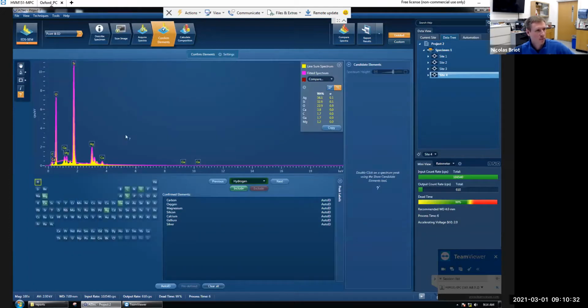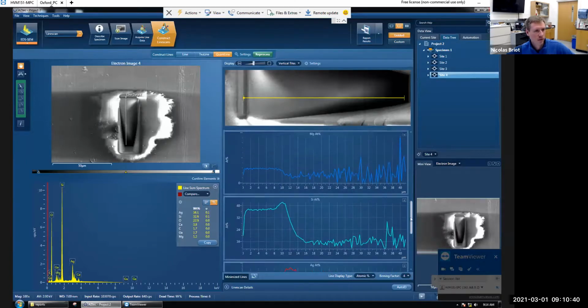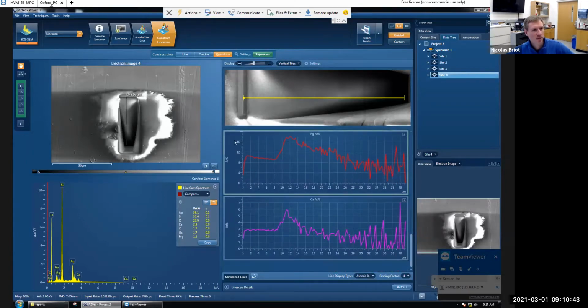And I could see silver. Let me see the line scan. Here we go. So if I go, I think it's at the bottom. Yeah, in silver here, you could start to see a significant amount of silver, and then it's just slowly decaying. So that tells me the technique worked pretty well. Where I'm a little confused is that if you look at the scale, we're talking about tens of microns, all right? So the question is, did we lose that much in the embedding, cutting, grinding, and polishing that we really disturbed the first 20, 30 microns? That seems a little brutal to me, but I guess that's what the numbers are showing. So that was the good news, that with the FIB cross section, you could see something here.